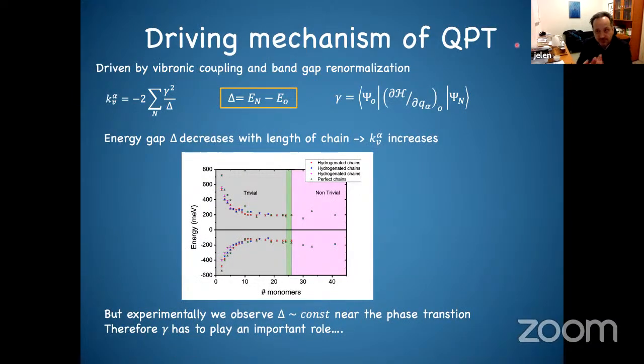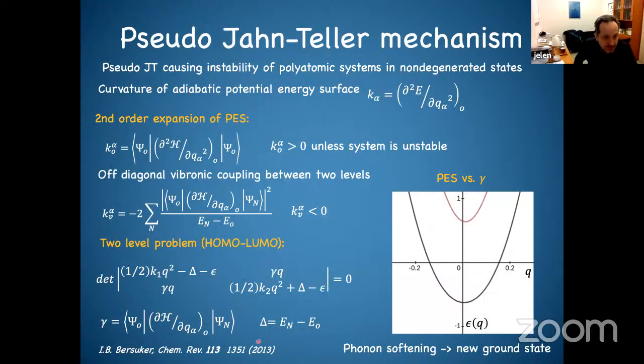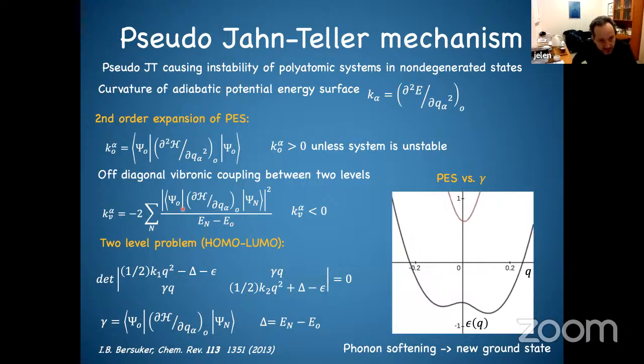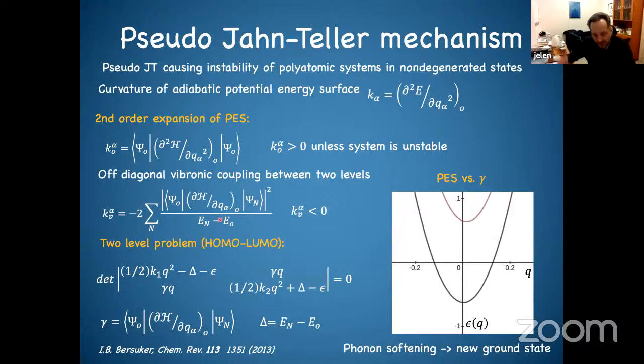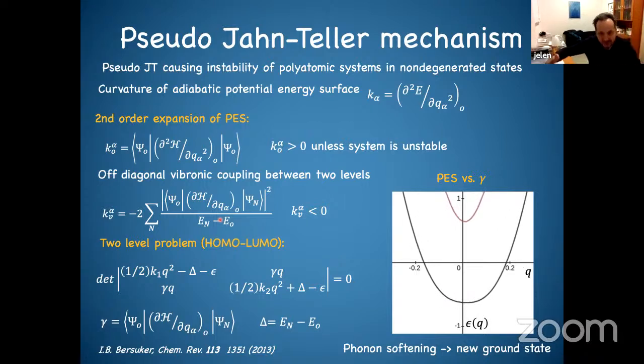So the driving mechanism for this transition from one, let's say, stable state, when I start to tune on this vibronic coupling, is as lower as the band gap is. So going just back, sorry, you can derive this one. There are two parts which make this strong or weak. The first part is basically this vibronic coupling, and the second part is the difference between HOMO and LUMO. So if the HOMO-LUMO gap is lower, the vibronic coupling is stronger. It's also that the excitation, or virtual excitation, of some electron gas due to this motion is easier.